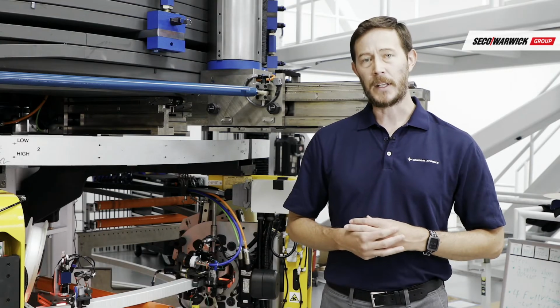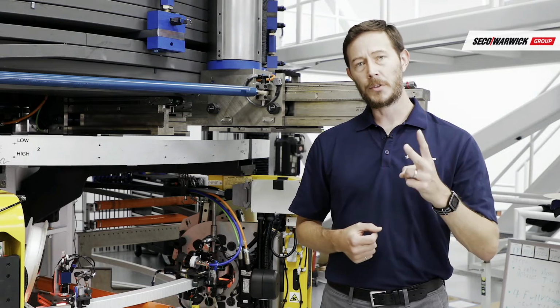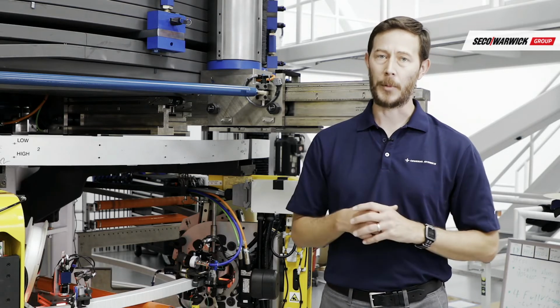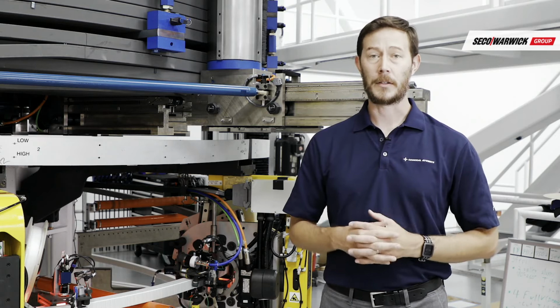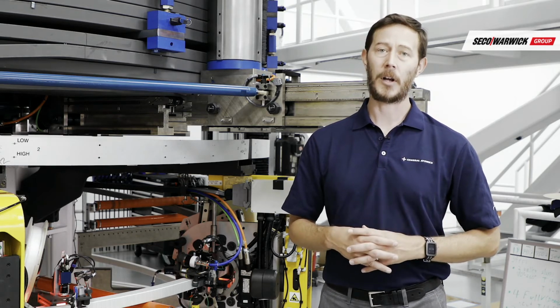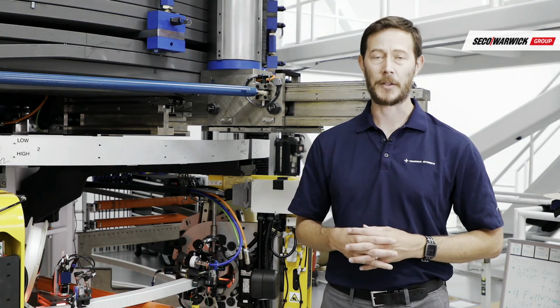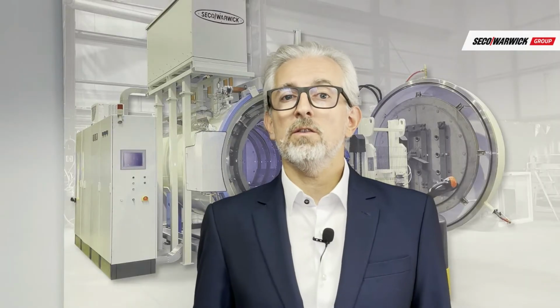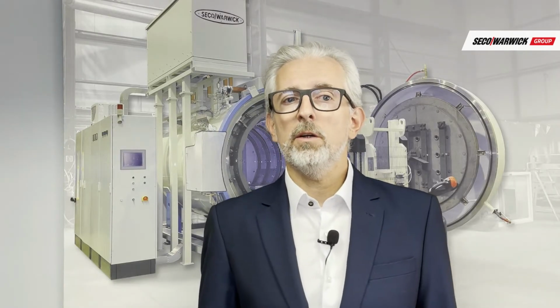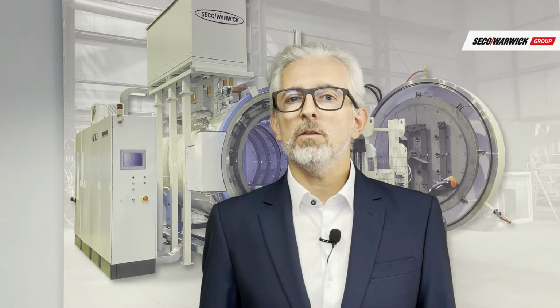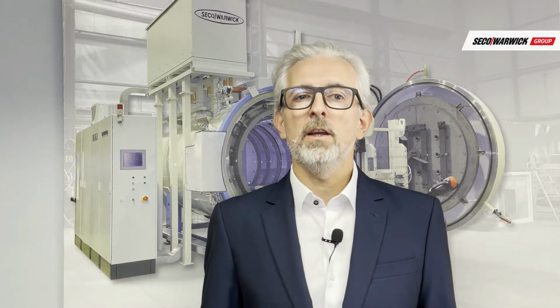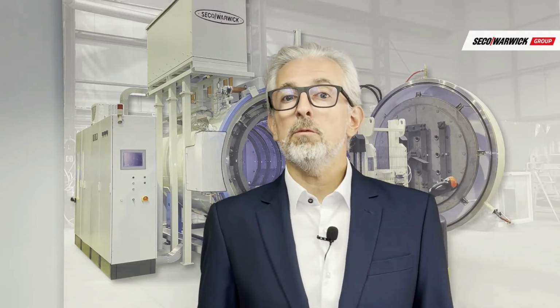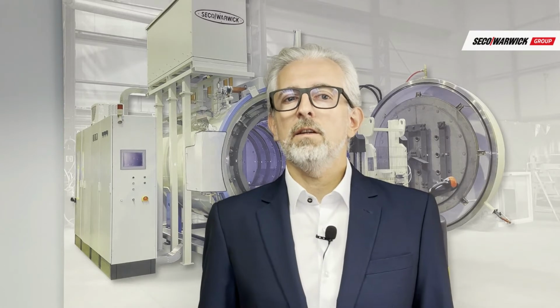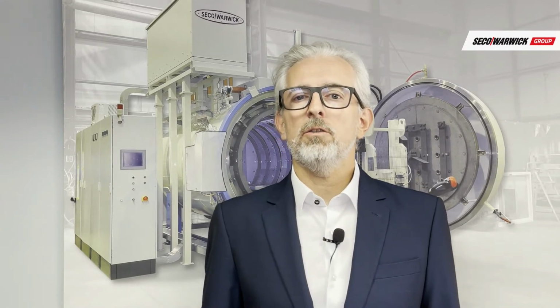When the process is complete, the conductor now contains 2 strands of superconductor for every 1 strand of copper. And from that point on, the superconductor is very brittle, and we have to take extra precautions not to damage it in our manufacturing process. This is a very conservative approach, but as we remember, we have 110 tons of precious load in the furnace, and the thermal treatment takes 5 weeks. Very serious task. Thank you, Nikolai, for explaining the reaction heat treatment process to our viewers.